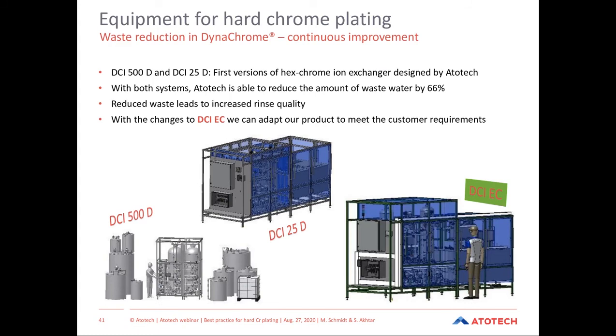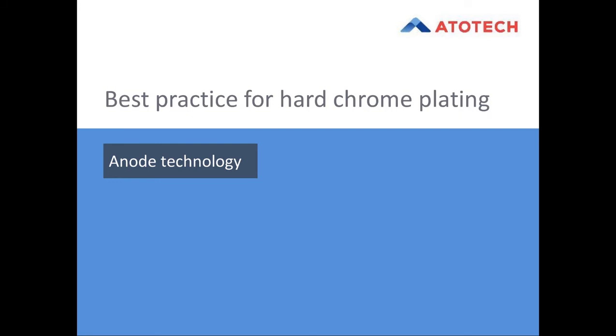As part of the wastewater system, we operate our Dynachrome lines with ion exchangers in order to remove iron and trivalent chrome from the plating bath. This is possible in different resin sizes depending on how much contaminants are built up. The columns can be from 25 up to 500 liters of resin. And as part of the high requirements for the automotive industry, these kinds of systems are required in order to keep the contaminant levels very, very low to have a good quality of the chrome plating.